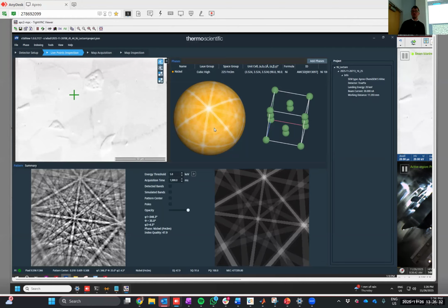That's a 50 micron scale bar for this case. I can make it smaller, but the microstructure is not interesting. So, mapping the whole surface with a step size of 500 nanometers for this experiment. The smallest step size I would like to do is 20 nanometers, and the largest on this microscope in this configuration is about 2 millimeters across the surface.